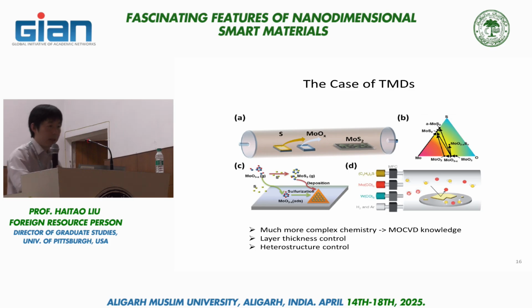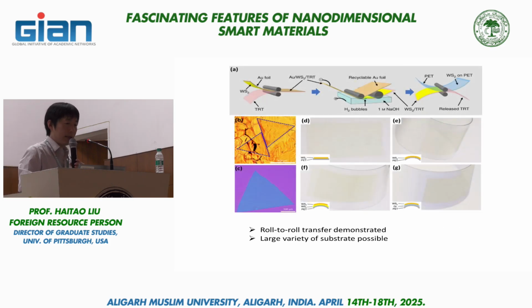Once you grow those materials, they are on the metal substrate. In this case, it's a gold foil that has been used. And this is the case where people grow tungsten disulfide, again, transition metal chalcogenides. And one important task here is how do you exfoliate that single layer of 2D material from the growth substrate into something else so that you can make more interesting devices.